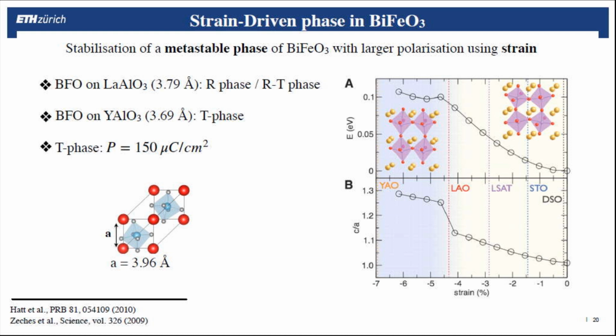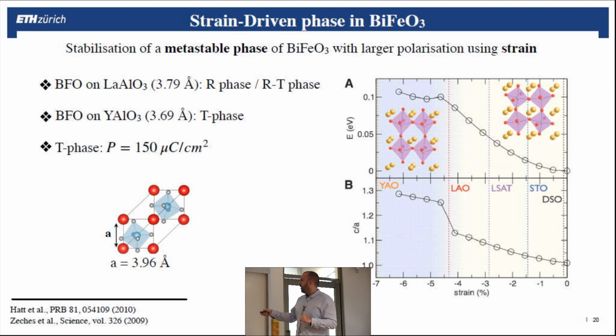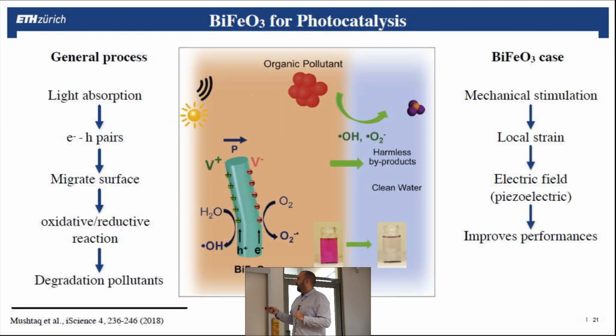And when one grows bismuth ferrite on top of these two materials, you can see that this applies strain. And these are numerical calculations, but are actually reproducing experimental results. And what you can see from here is that when you apply strain, let's consider this one, you are actually increasing the energy, because that's not what the material would like to be, the spacing. But what happens is that when you compress in plane, it relaxes out of plane. And we saw that the out of plane is also linked to the polarization. So when you compress this material until these large values of strain, then the polarization increases. And it goes from about 100 to 150 microcoulomb per centimeter square. So about 50% more than it was initially. And this shows that by changing the in-plane, you can also induce more ferroelectricity or a larger polarization.